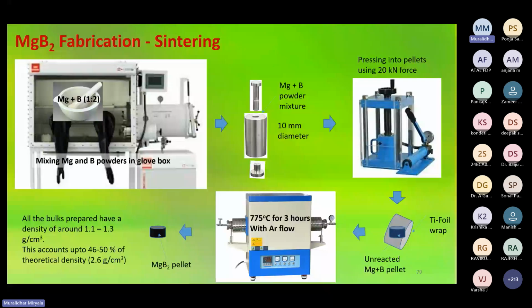This is simple processing. When your nanoboron is ready, we have to mix the magnesium and boron in the glove box. Otherwise, the magnesium will react with the oxygen in the air and form MgO, which is a non-superconducting particle. That's why people normally do the mixing in the glove box, then pressing and sintering for just 3 hours, and you get the superconductor. It's very easy, low cost, lightweight.